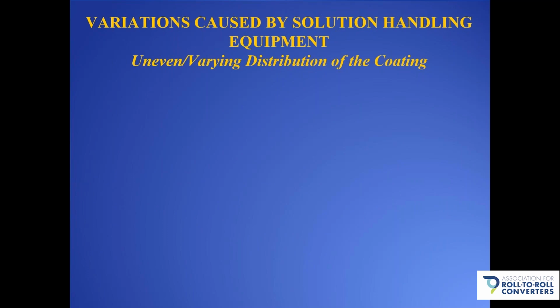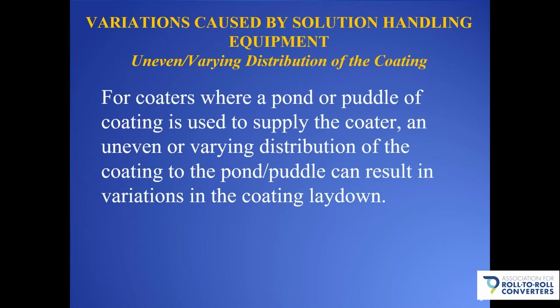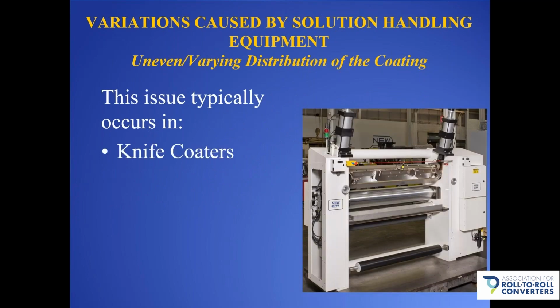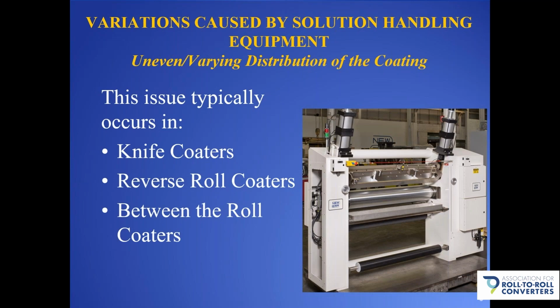Another issue is uneven or varying distribution of the coating. For coaters where a pond or puddle of coating is used to supply the coater, an uneven or varying distribution of the coating to that pond or puddle can result in a variation in the coating laydown rate. This issue typically occurs in coaters such as knife coaters like you see here on the right, reverse roll coaters, and between the roll coaters. Now this issue really shows itself when you get into higher viscosity coatings where the coating itself doesn't have a tendency maybe to flow out and give a uniform distribution within the pond or puddle.